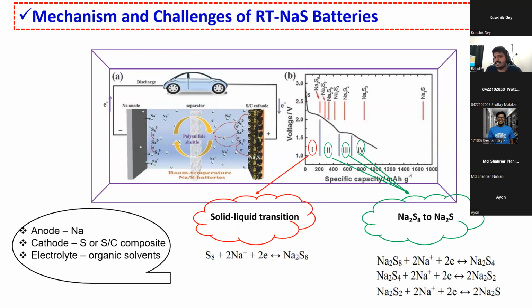Now, when we talk about the experimental voltage, this is basically a voltage profile, plotted between the voltage and the specific capacity. As I previously told, the sulfur is in the S8 form, and during the discharge, S8 will convert to Na2S8. As I told previously, Na2S8 is in the liquid phase, so it will go to the electrolyte rather than staying in the electrode. That's called the shuttle effect, and this is basically a solid to liquid transition. And this is the reaction.